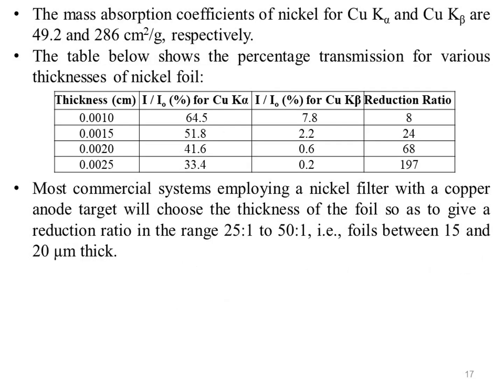The mass absorption coefficients of nickel for copper K alpha and copper K beta are 49.2 and 286 centimeters squared per gram respectively. The table below shows the percentage transmission for various thicknesses of nickel foil, and this is the thickness in centimeter. Here is I over I naught percentage for copper K alpha, and here is I over I naught percentage for copper K beta, and this is the reduction ratio.